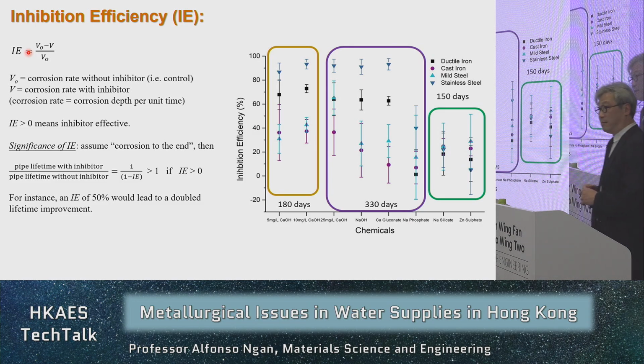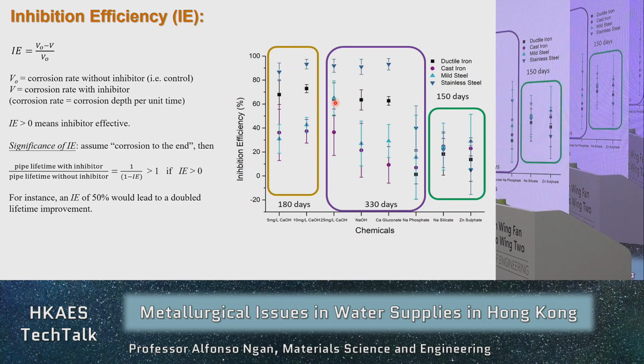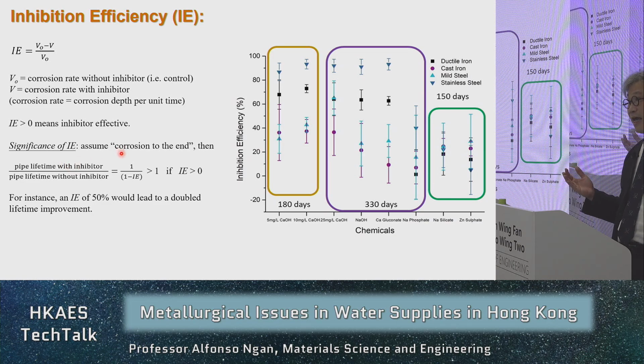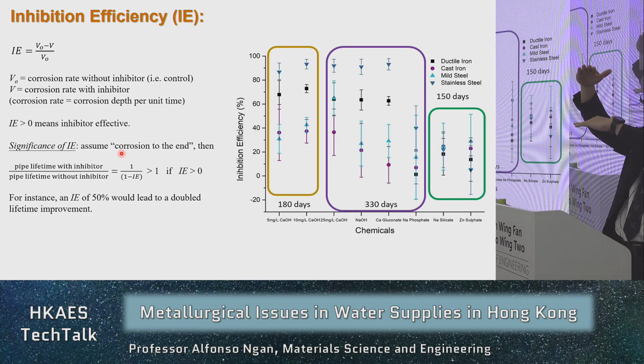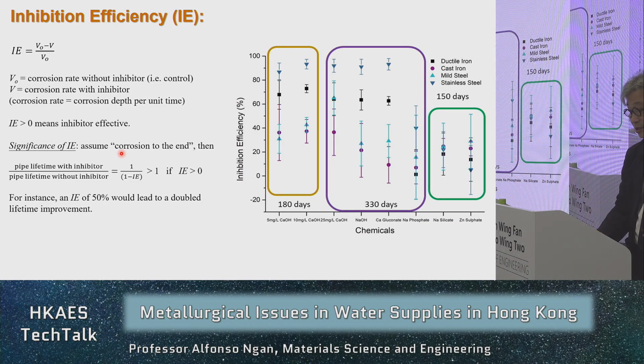So basically in all the conditions that we have tested, that is the 0 mark. So the majority of the data that we have tested show that the inhibitors will be able to slow down the corrosion for different materials as well and different durations. Okay? And if we assume corrosion to the end, so no pitting, no cracking, so you take a slab and then let corrosion reduce the thickness to the end, this ideal condition, if IE is 0.5, so that sort of value, which is not uncommon from our data, the improvement in lifetime will be doubled. All right, so if you have an IE of 50%, that means that your metal will corrode with a lifetime of 1 time more, right, or twice the original. So that's the sort of idea of the significance of this IE.